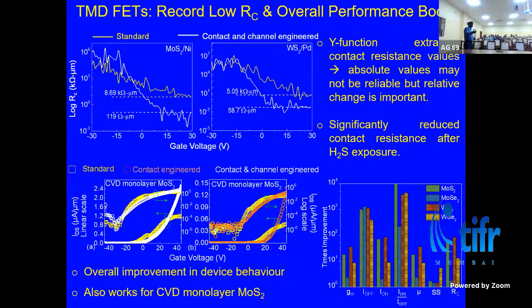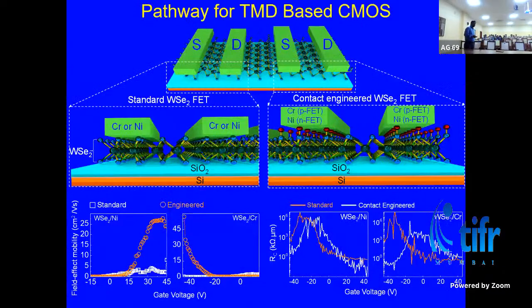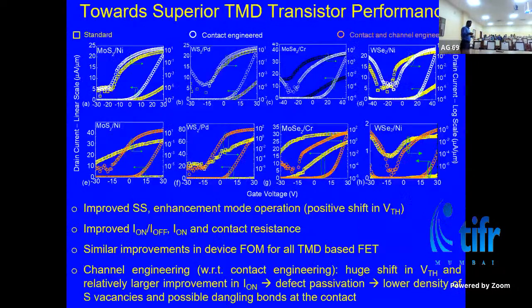And if you measure our contact resistance, which was close to the so-called quantum limit, say 10 to 5 kilo-ohm micrometer, it came down to 100 to 50 ohm micrometer. Of course, we also compared all the other transistor parameters, and since the channel was passivated, with the contacts the channel gets better. All the other performance figure-of-merit parameters are also significantly improved. Now, if you remember, I told you about these donor states and the acceptor states being increased, right? Whatever engineering I did here is all using those donor states. So this is all N-type transistor.